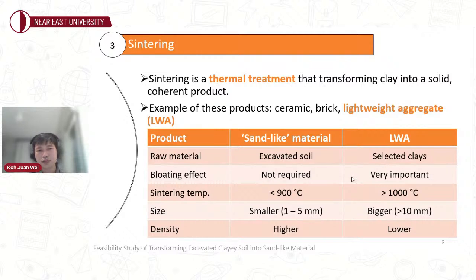As for the sintering temperature, our product is sintered below 900 degrees Celsius, and lightweight aggregate is normally sintered above 1000 degrees Celsius. The size of our material is smaller, about 1 to 5 mm, while lightweight aggregate is bigger. Similarly for density, ours is larger and lightweight aggregate will be lower.